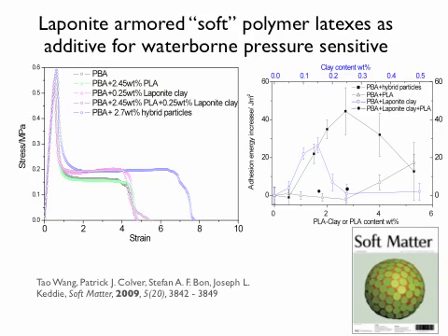So let's take this polybutyl acrylate latex, and we add 2.45 weight% of naked polylauryl acrylate particles. Now, if you think about this, you have a soft series of particles, and you add more soft particles. So there shouldn't be a difference. And there isn't. So the green line behaves exactly the same, or roughly the same, as the black line.